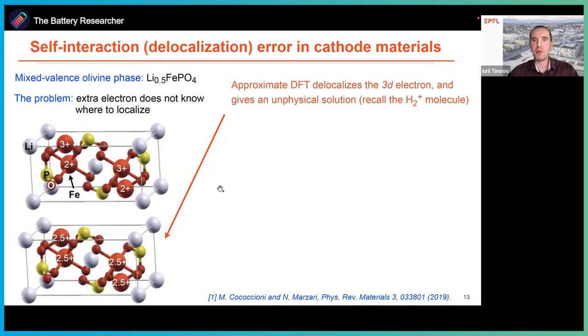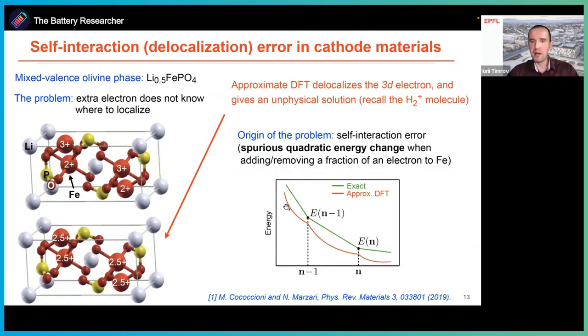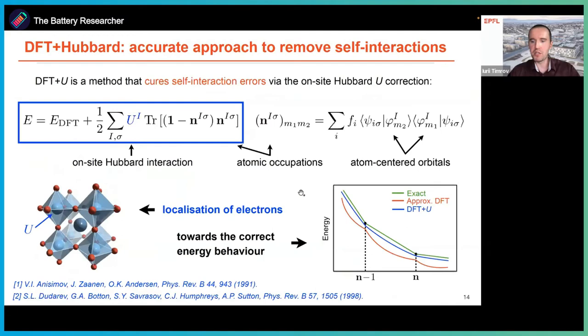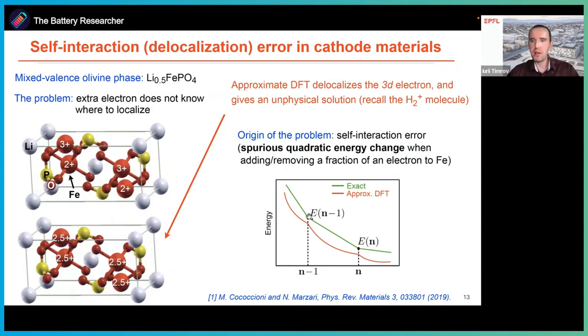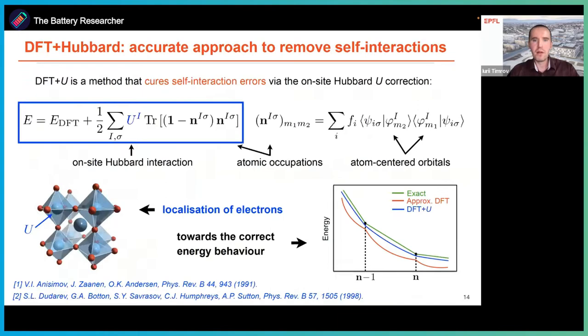It's really an issue. And again, as I said before, this is linked directly to the energetics, how energy behaves as a function of the number of electrons in the 3D manifold. So N is the number of electrons in the 3D manifold, and the exact and correct solution must be in green, the piecewise linear one. You see straight lines connecting these integer values, but approximate DFT gives us parabolic-like or quadratic-like behavior, which is wrong. So we need to solve this problem somehow to be able to model battery materials.